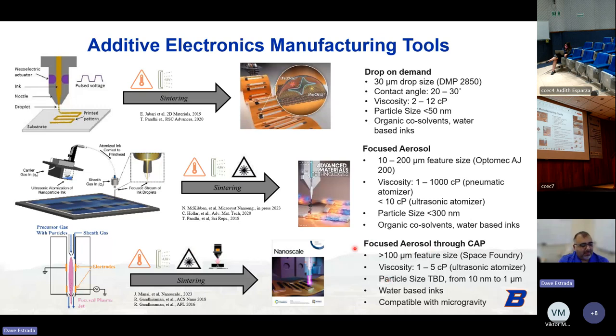So the feature size, this is still, I would say, an early stage system, but we've gotten down to about 100 micron feature size. So there's still work to do in increasing the spatial resolution. Viscosity is in the 1 to 5 centipoise range. Particle size, we've been able to print larger aspect ratio nanorods, nanotubes with this printer, up to about 1 micron in length. And it works best with water-based inks because you are running it through a plasma. So we try to avoid harsh organic solvents.